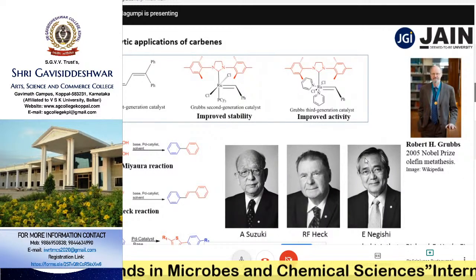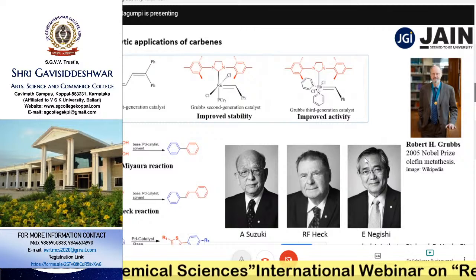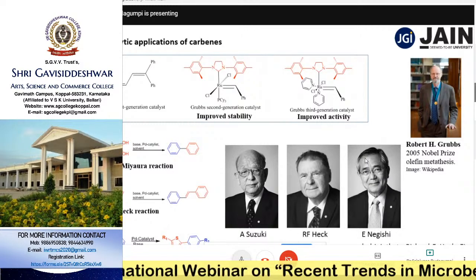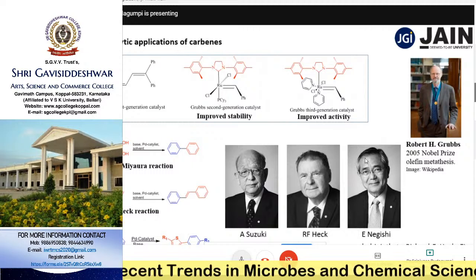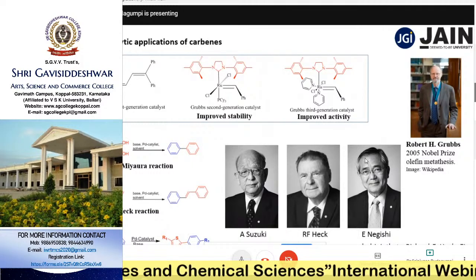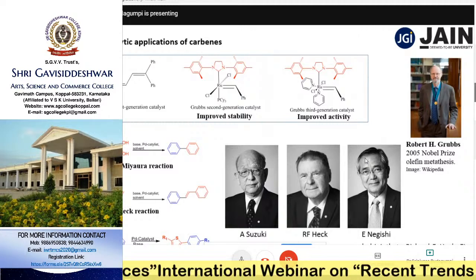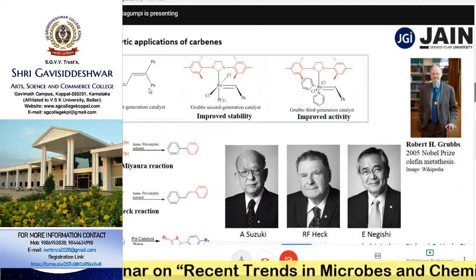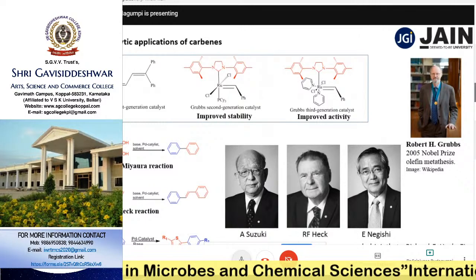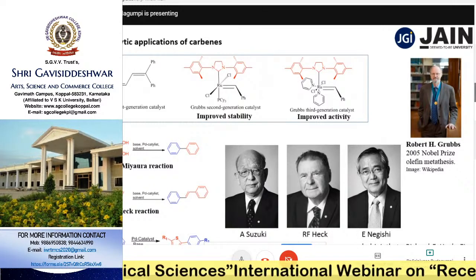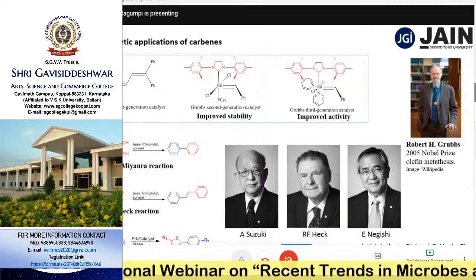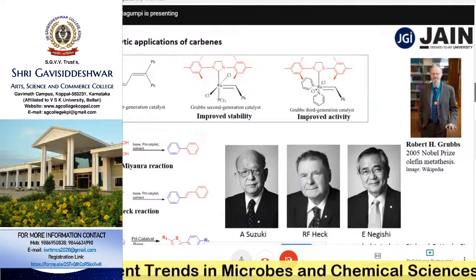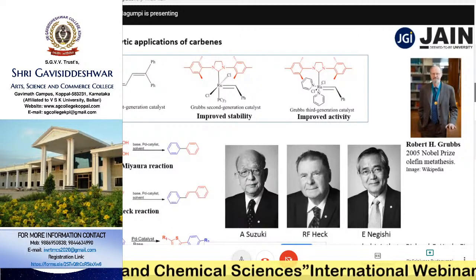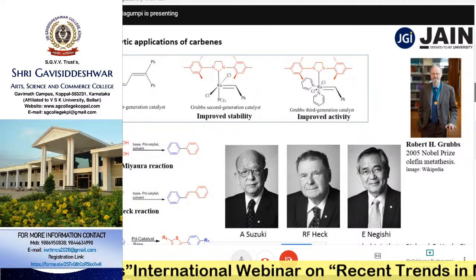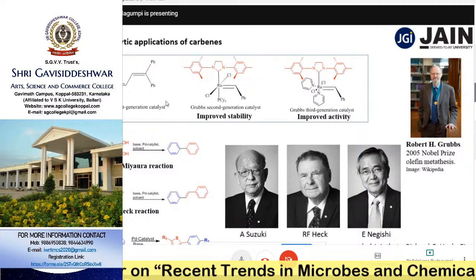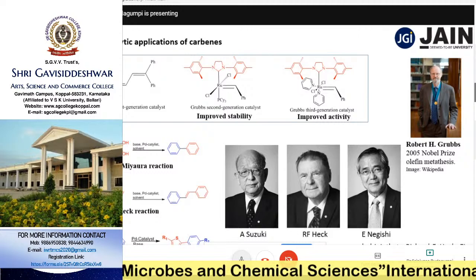See, catalytic applications are well endorsed in the literature. So for example, Grubbs catalyst, of course, Robert H. Grubbs, who is a Nobel laureate in 2005, along with Richard Schrock, got the Nobel Prize in 2005 for the fantastic discovery of olefin metathesis catalysis. If you look carefully at the structure here, it is unstable, right? During the catalytic process, this particular system is highly unstable because the ruthenium center is not stabilized by any strong field ligands, right? Though it has one carbene ligand here, this was not stable enough to maintain the active species for a longer time. Later they replaced one of the triphenyl phosphine ligands by a carbene ligand.